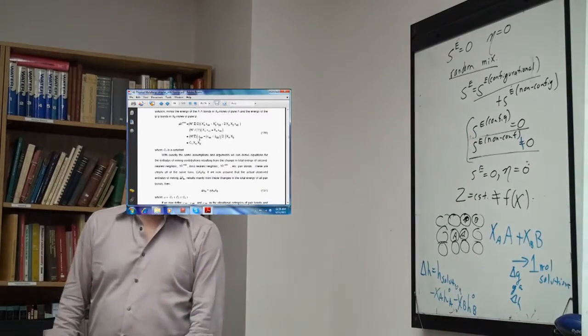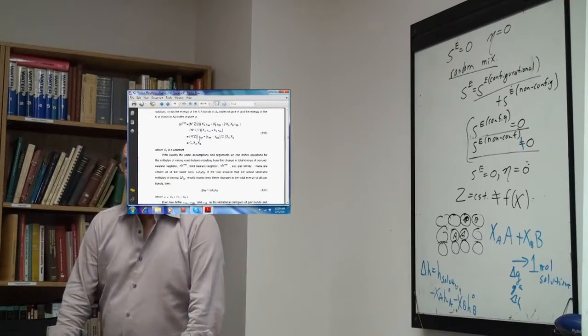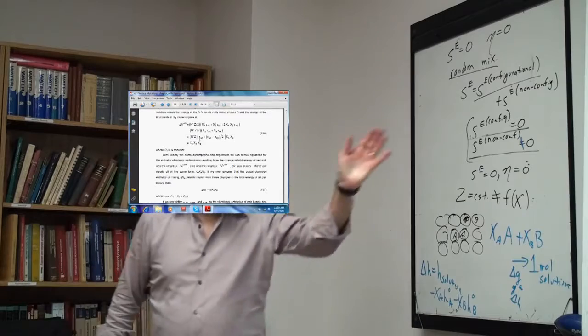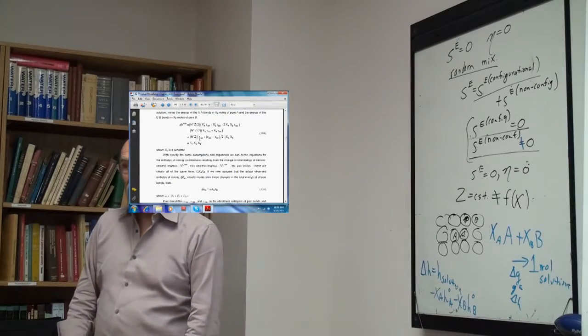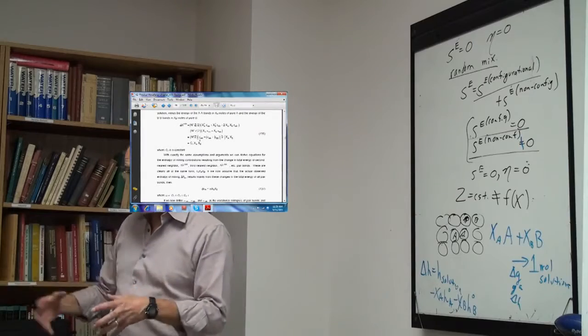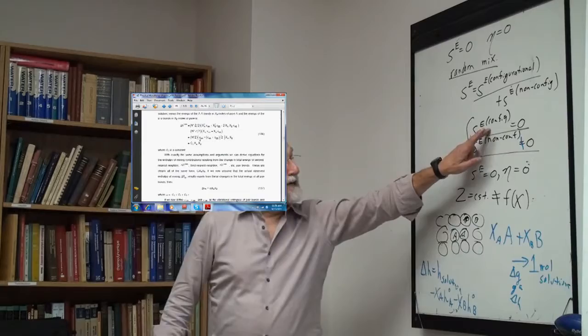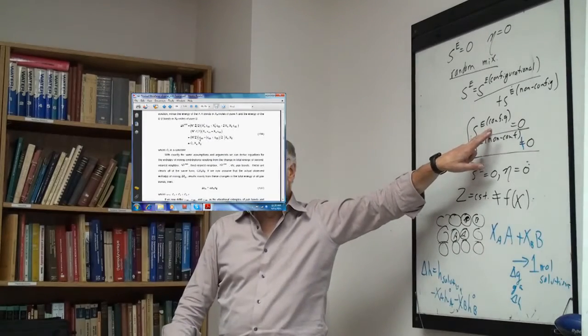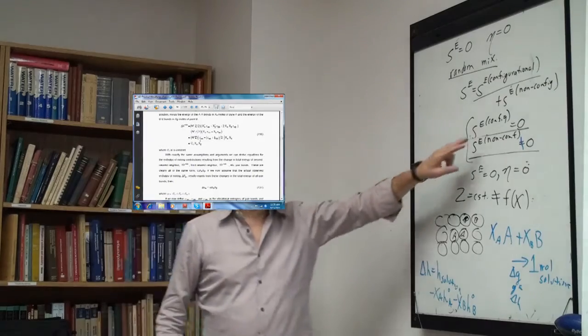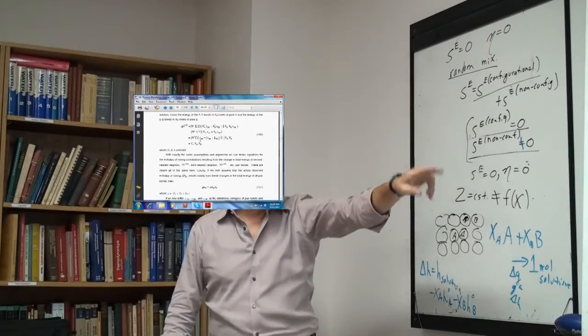If delta H is negative, it's because the AB bonds are stronger than the AA and BB bonds, and so you will get more AB pairs than the ideal. In an ideal solution, the number of AB pairs is 2X_A X_B. If epsilon AB is negative, it'll be bigger than that, and the number of AA bonds will be less than X_A squared. So in that case, the excess configurational entropy clearly is not zero. So there's this sort of logical flaw. You're saying S^XS is zero, then you're saying delta H is non-zero.